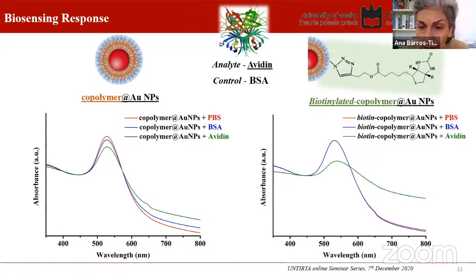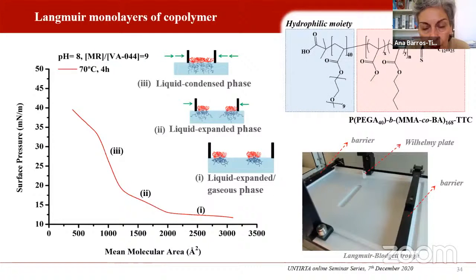Instead, in the presence of biotinylated copolymer gold nanoparticles, when in the presence of avidin, the response was pretty clear. As you can see, the particles aggregated, therefore, it means that the nanoparticles have interacted specifically with avidin. So we had the confirmation that this strategy was okay, but still we wanted to assess how this polymer shell was actually interacting with the analyte avidin.